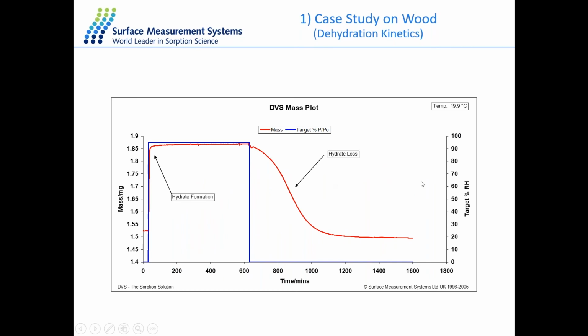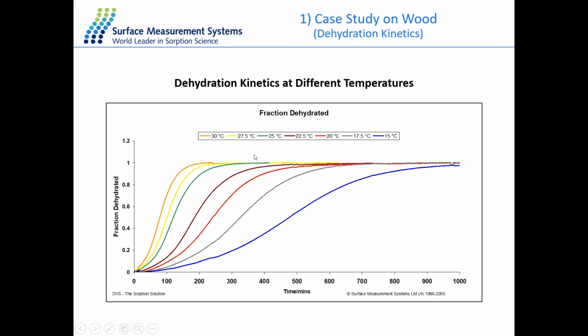So apart from the water uptake and water diffusion, we can also set up a method starting directly from 90% RH and then drying at 0% RH to study the dehydration kinetics. So we can compare the sample at different temperatures, like this one. So here we summarized the same sample at different temperatures, plotting against the time and fraction of dehydration. And here you can see that by increasing the temperature, the dehydration kinetics will be faster on this kind of sample. So these are just some very typical moisture sorption experiments we can perform with the wood samples.